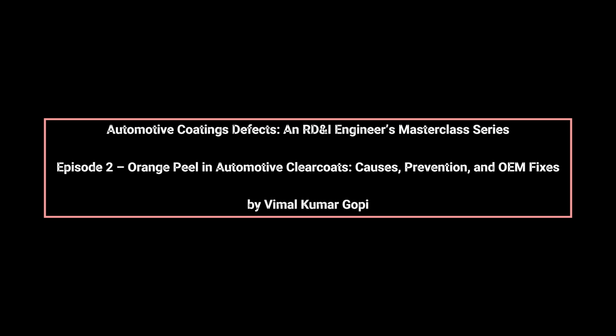The total solvent balance must be carefully designed to match the expected film thickness, ambient temperature, and relative humidity. Excessive dry film thickness exacerbates the problem because the top layer can skin while the inner film still contains tail solvents, creating trapped pockets of differential flow that manifest as texture.